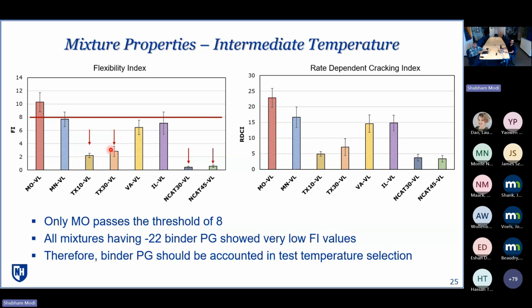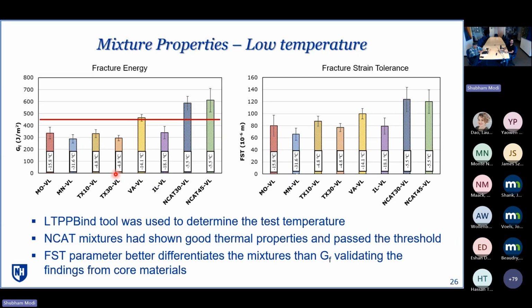And therefore, somehow we have to come up with a testing temperature selection that incorporates the binder PG into it. Location PG at least. Yes, and the location PG from the LTPP Bind dataset as well. That leads to the low temperature testing, and here we have selected the temperature based on the LTPP Bind dataset, depending on the geographical location.